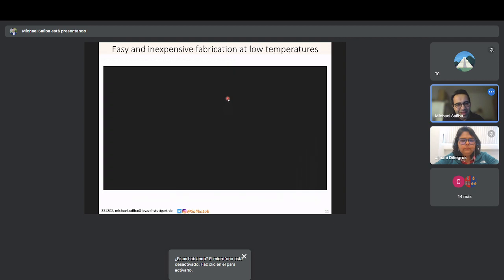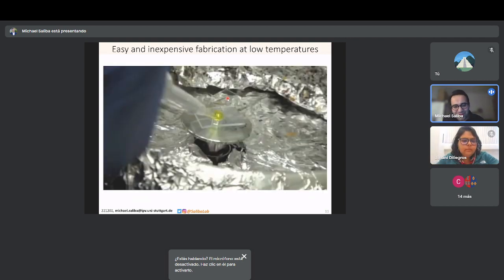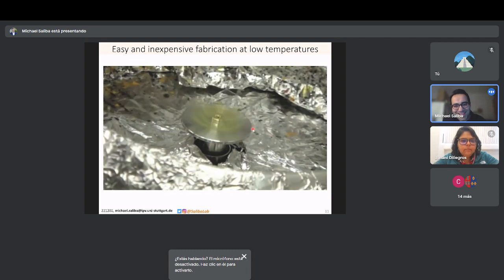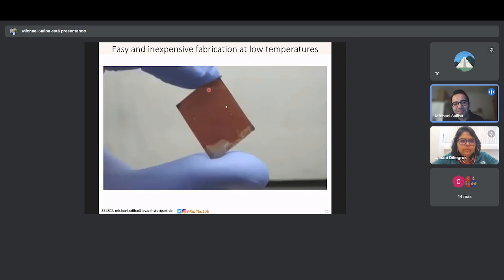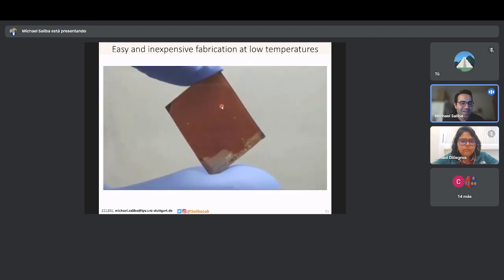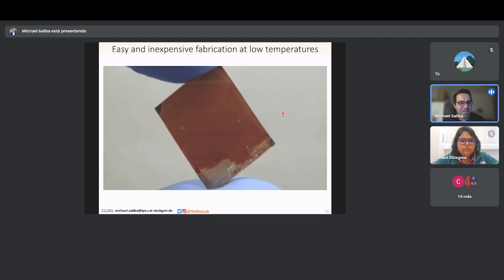So perovskites are easy to make. This is a video that we took in Oxford back in the days. You take the perovskite ink, you spin coat it, and that's it. So this film, which you'll see in a second, when contacted correctly, is a solar cell. So it's very accessible. The feedback cycles to make a solar cell from bottom to top takes only about a day, 2 days, unlike III-V semiconductors or silicon that can take in a lab fabrication scale many weeks even.